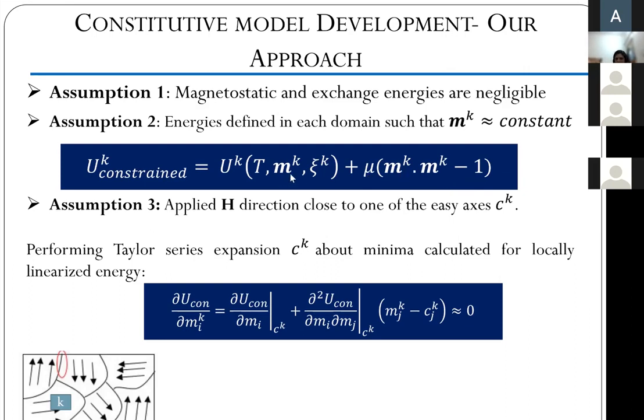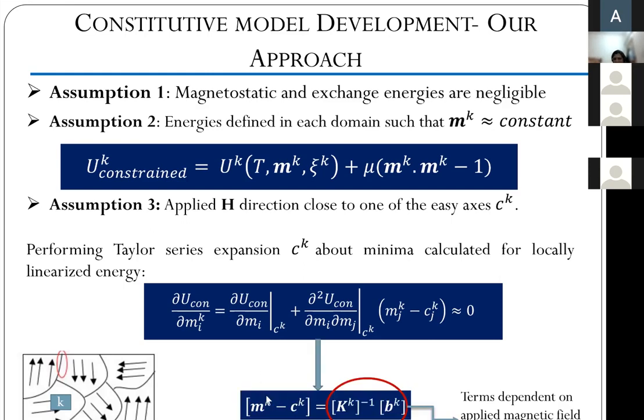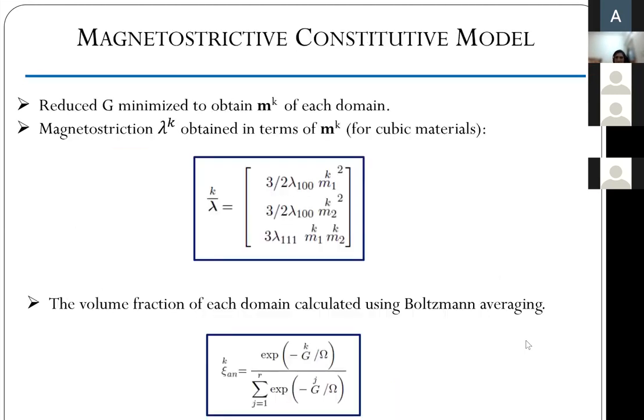So this is a constrained minimization. We do it in terms of magnetization, because we wanted to avoid the whole mess of dealing with angles and duplication of angles. So we do a Taylor series expansion of the free energy about each easy axis, and then do a minimization within each domain. The solutions to this give us the orientation of M for a given applied magnetic field direction. And then finally, what we end up getting is a nice linear equation, where this matrix K and this vector B only depend on the applied magnetic field and applied stresses. Magnetostriction is then defined in terms of magnetization. Again, this is reduced through careful symmetry arguments.